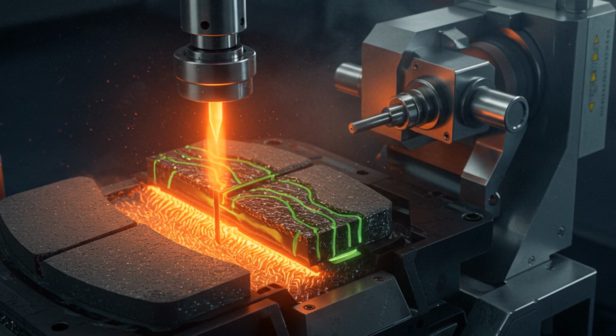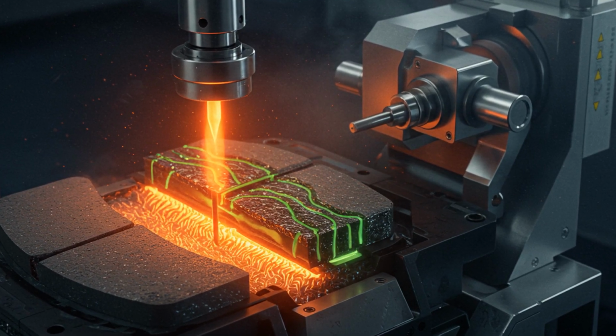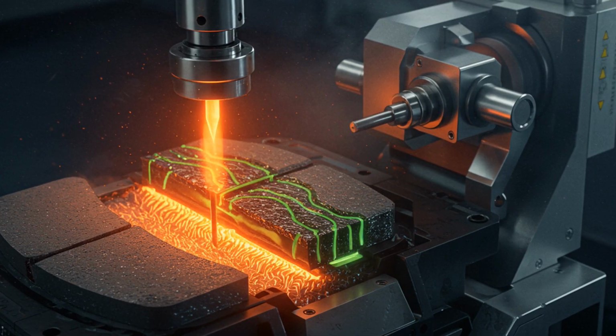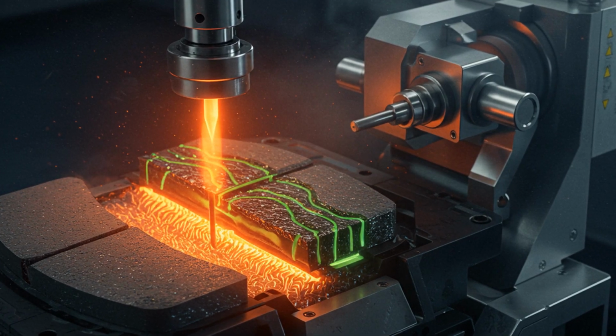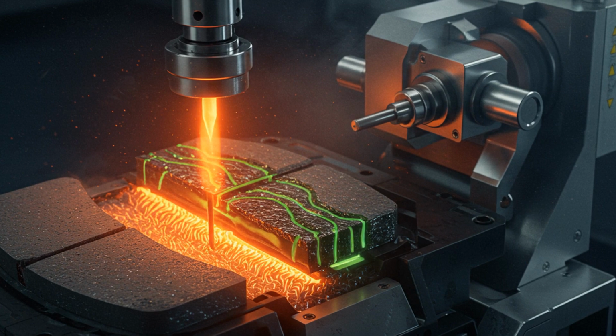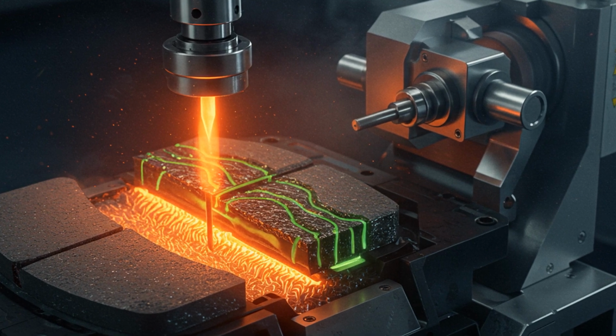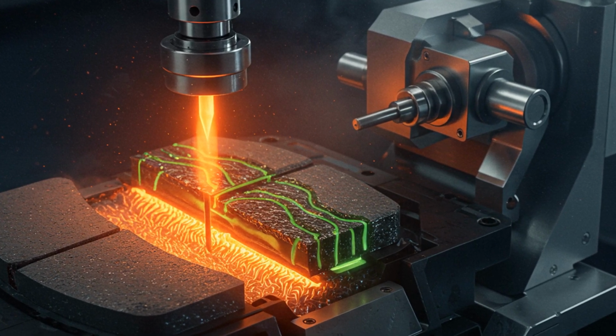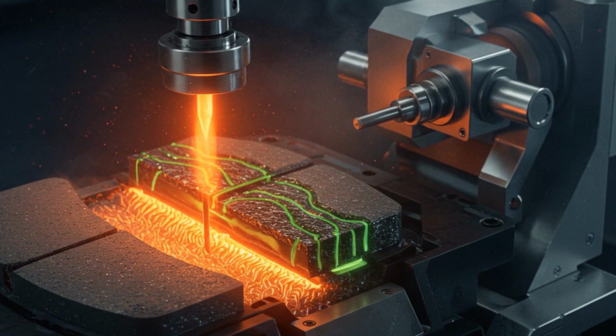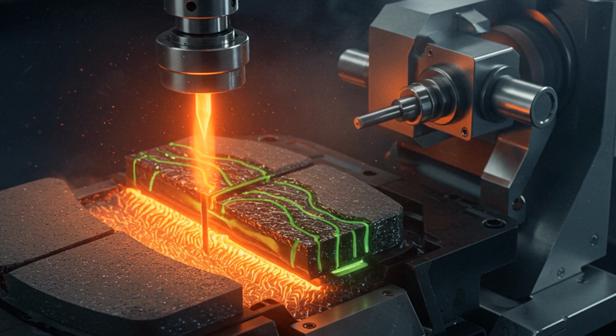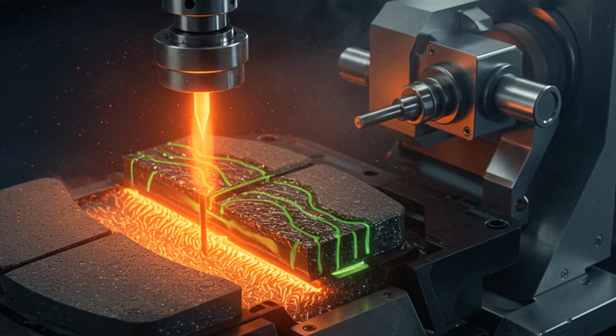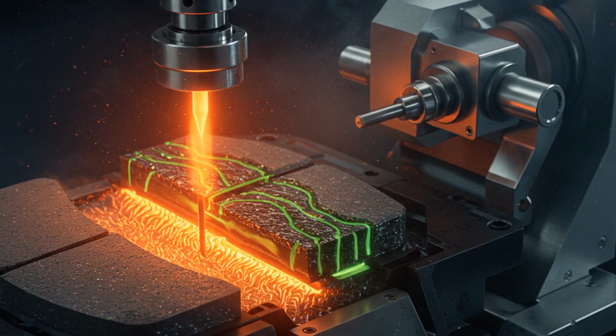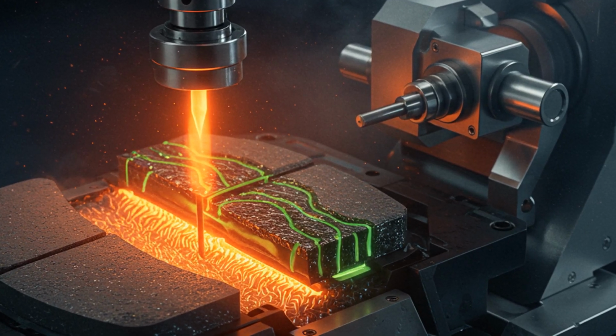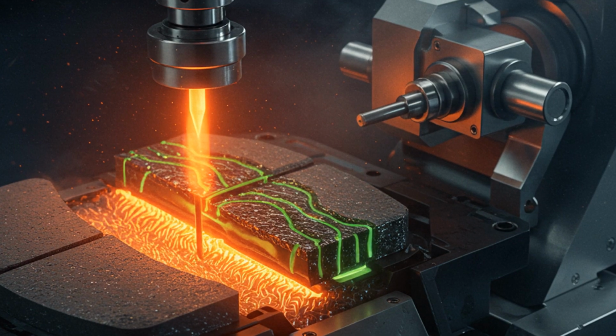Thickness tolerances are held to tenths of a millimeter because pad wear determines service life. After curing, pads are ground to precise profile, grooved to remove gases and dust, then bonded to steel backing plates using high-strength adhesives and rivets. Each pad undergoes friction testing on a dynamometer: simulated stops at various speeds, measured wear rate, coefficient of friction stability over temperature, and fade resistance up to surface temperatures of 200 to 300 degrees Celsius.